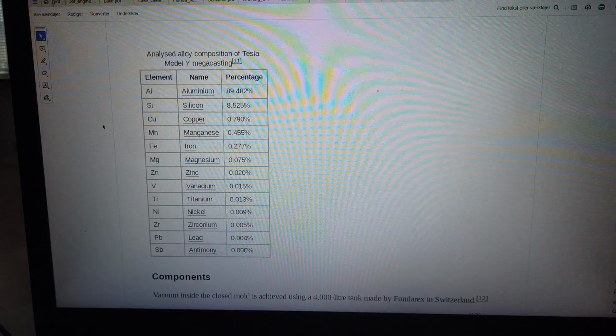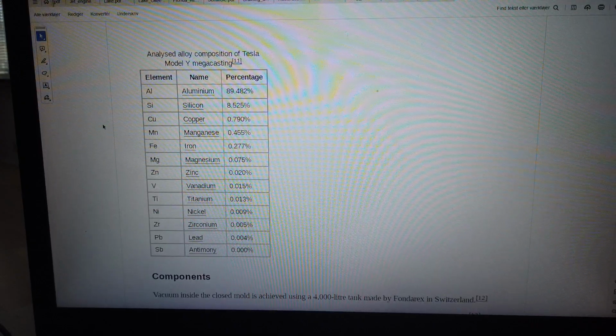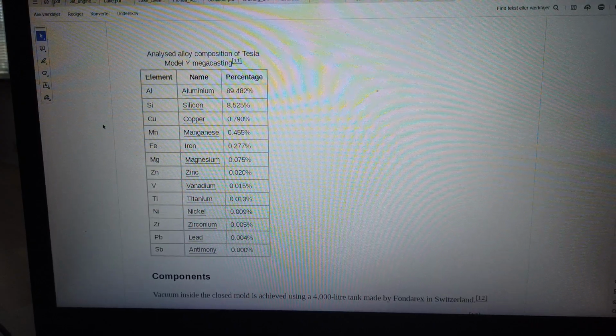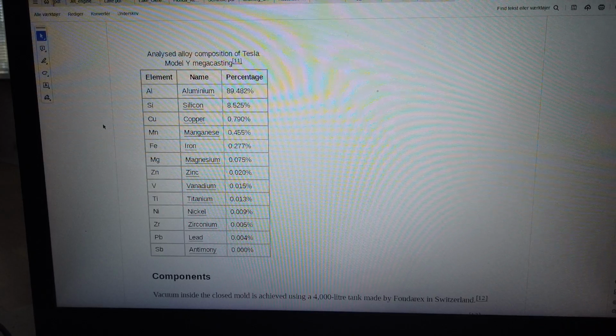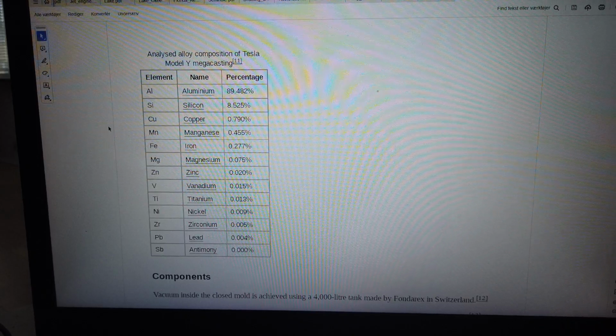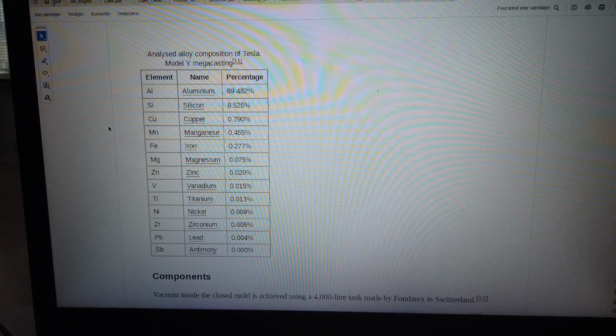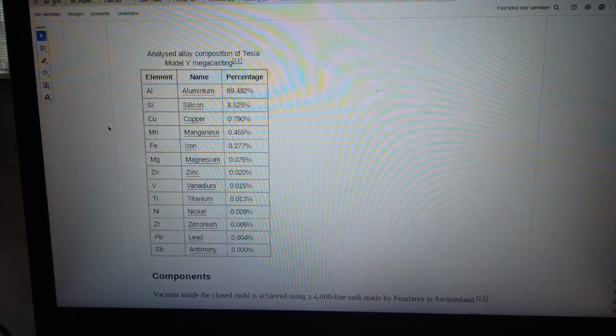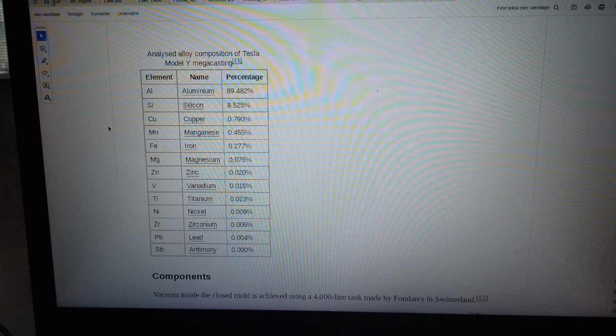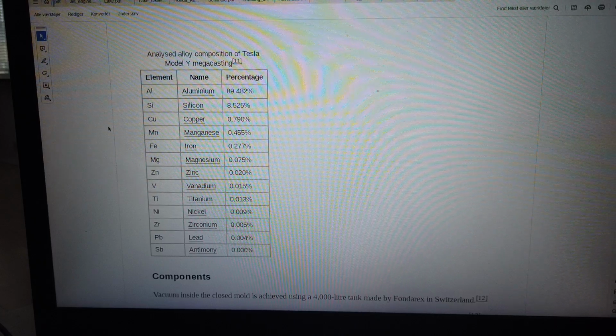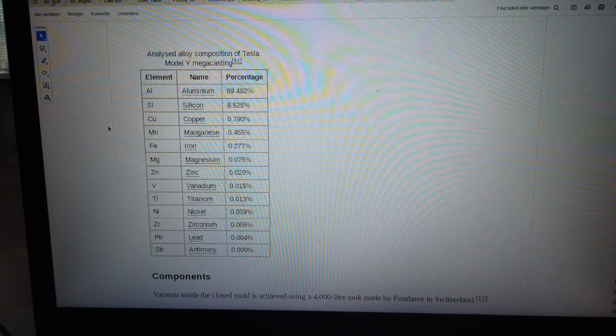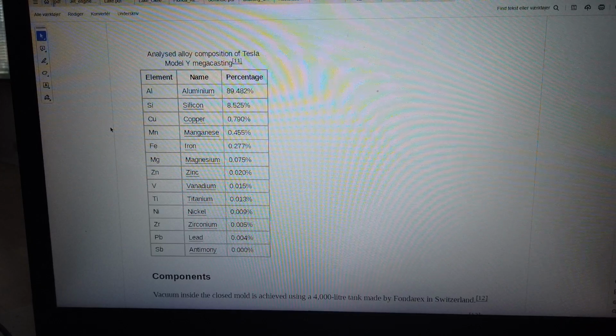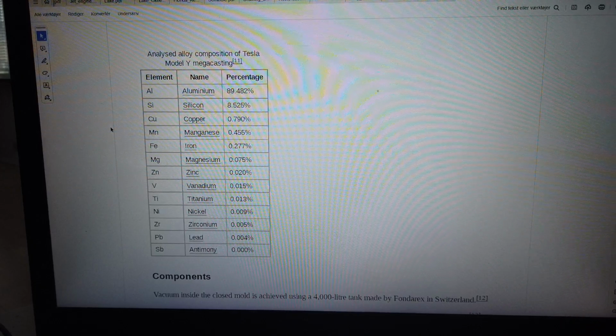Analyzed alloy composition of Tesla Model Y mega casting. 11. Element name, percentage: aluminium 89.482%, silicon 8.525%, Cu copper 0.790%, Mn manganese 0.455%, Fe iron 0.277%, Mg magnesium 0.075%, Zn zinc 0.020%,